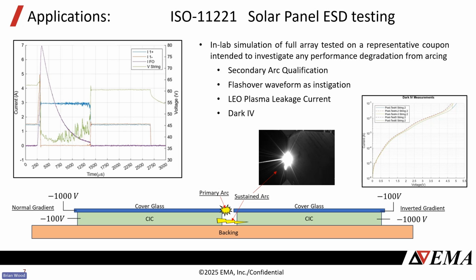But then once that primary arc ceases to exist, you would hope that the sustained arc would also stop. And that's this waveform that you see here as an example of that, where you see the IFO stopping, and you see all the other currents kind of going back to their nominal values. And that's what you want to see. What you don't want to see is that primary arc ending and then those currents persisting. And they can persist for, if you're looking at the time scale here, that flashover is lasting over 1,000 microseconds.